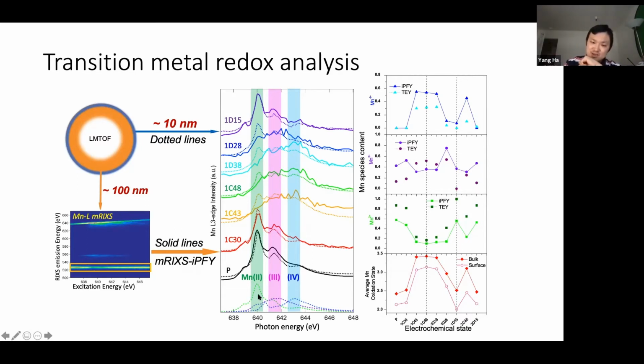And then we can do this principal component analysis for each sample. So we know at each state of charge what type of manganese, how much manganese 2, manganese 3, and manganese 4 in each sample, both at the surface and in the bulk. And eventually we can add up these valences, and we can know the average valence of each state, both in the bulk and in the surface. So here in this curve, we can see the bulk and the surface mainly follow a similar trend. So it's higher valence when it's charged and lower valence when it's discharged. And the surface is generally more reduced than the bulk.